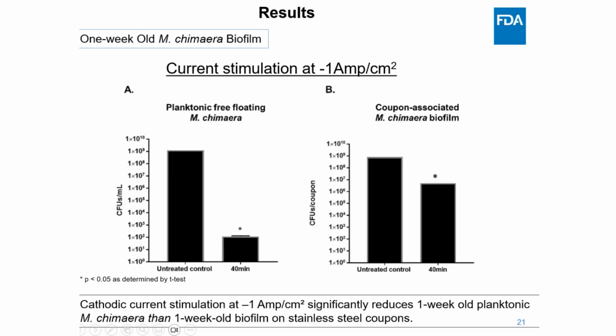Following these strong results we observed with the early stage biofilms, we next tested whether cathodic current stimulation could also disrupt more mature NTM biofilms. So we repeated the experiment using 1 week old M. chimaera biofilms and applied this minus 1 amp current density for 40 minutes, targeting both coupon-associated biofilms and free-floating planktonic cells.